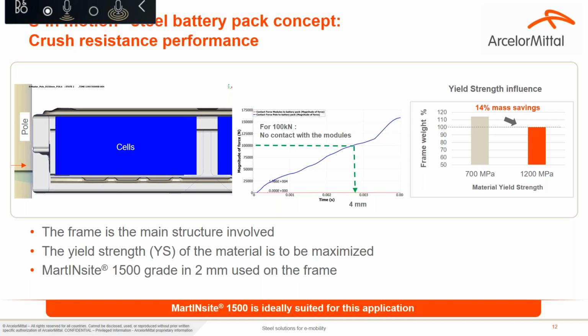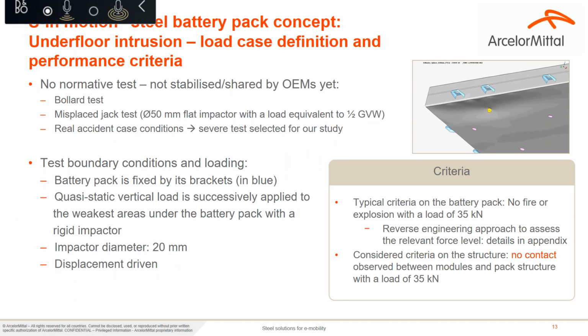We would like to mention that for this test, the frame is the main structure involved. The yield strength of the material of the frame is very important, and it has to be maximized. That's why we have selected Martinsite 1500. And you can see in the right graph that if you use a lower grade, 700 MPa for example, you increase the weight by 14%. So Martinsite 1500 is important to keep the weight of the frame as low as possible.